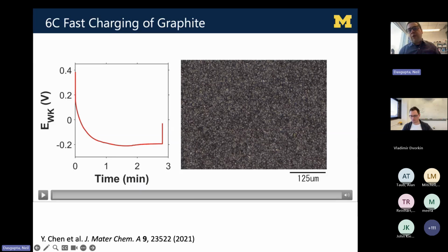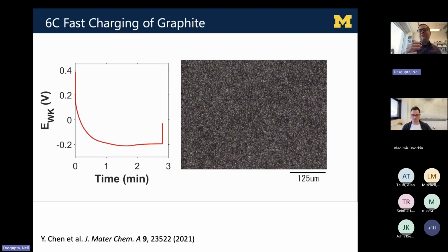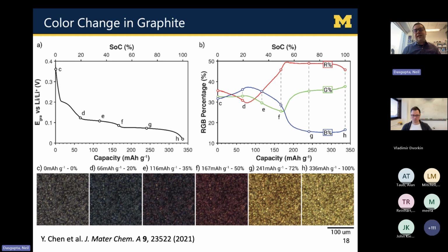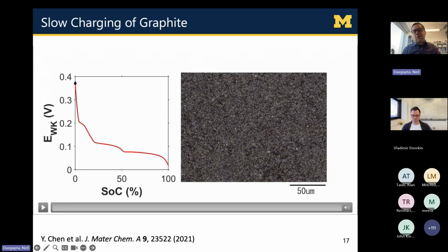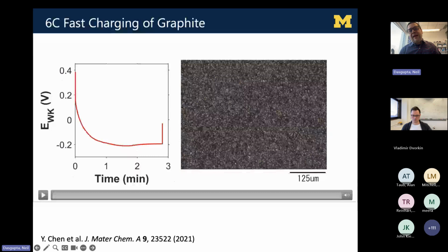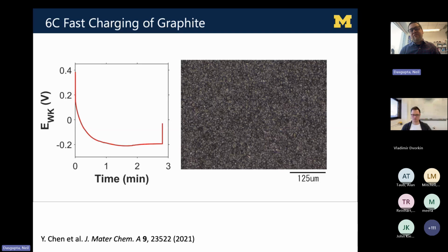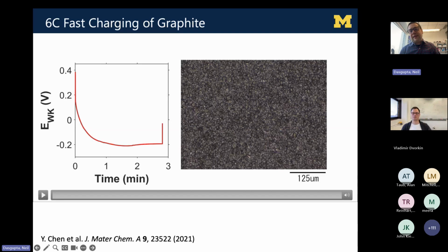Here right away, even before I play the video, if you look at the left-hand side, you can see the voltage trace looks very different for fast charging than slow charging. Whereas the slow charging had these three very distinct plateaus that come from the thermodynamics of graphite, when we have fast charging conditions, we see the voltage of the graphite quickly drops below zero on the y-axis and then reaches a local minimum and then reaches a plateau.